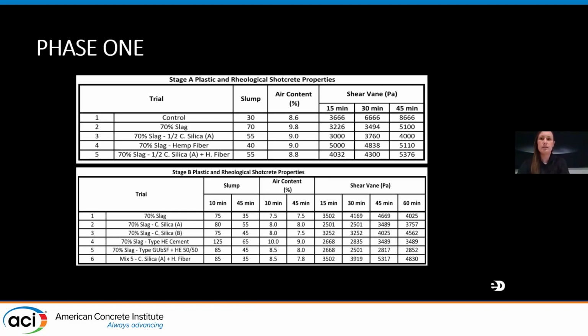On the screen is one set of trials that we initially tested. With each new stage, we took lessons learned from the previous trials to optimize the mixtures and better replicate real-life conditions by adding delays to simulate batch, travel, and staging times based on where the concrete would be batched in the city and then where the location of the site was. The plastic properties of each mix were measured at the batch plant and then also measured when it arrived on site and after simulating 30-minute transport time. The rheological properties were also measured at 15, 30, 45, and 60-minute increments.